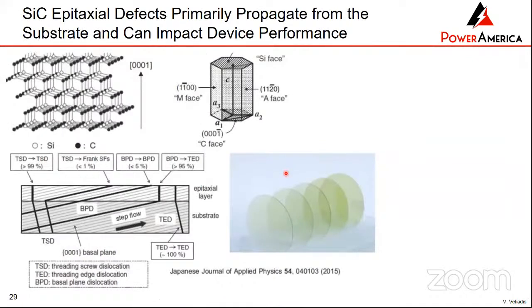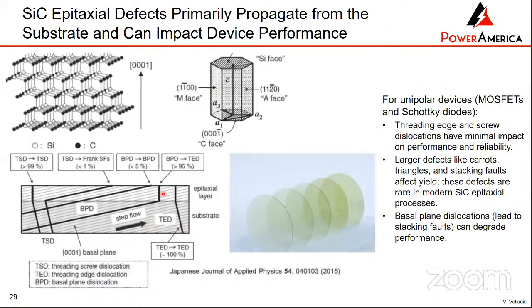So if you look at the silicon carbide substrate, which is the wafer right here, the substrate, you start with a substrate in this process that I just showed you in the previous page, which is more complex and therefore more expensive than silicon. And then you put an epitaxial layer, which is a high quality layer where the device is going to be built. And the idea behind doing the epitaxial layer well is to make sure that defects in the substrate do not propagate into the epitaxy.